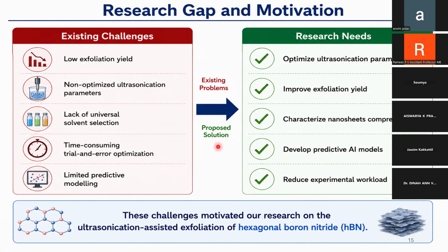So what you can actually propose is that you need to optimize the ultrasonication parameters. Like I said, you tune the optimization parameters like time, power, and the solvent you are using. Thus, by optimizing it, you can have the better yield. Okay, so by doing that, definitely you can improve the exfoliation yield. And once you get the better exfoliation yield, it's not just the amount you're getting, it's the quality of nanosheets you are getting that matters much.